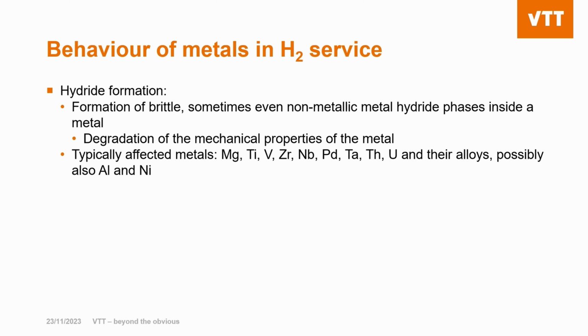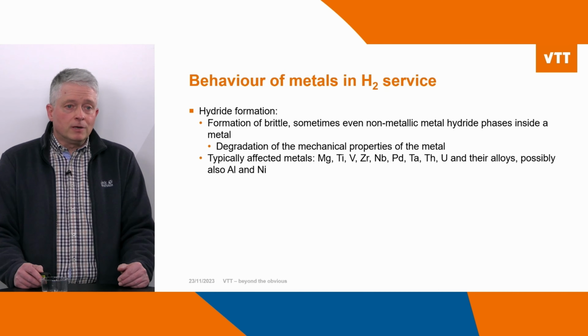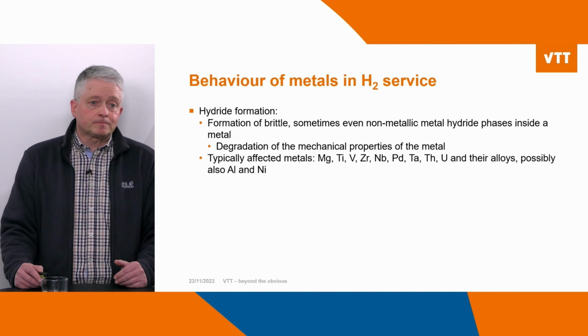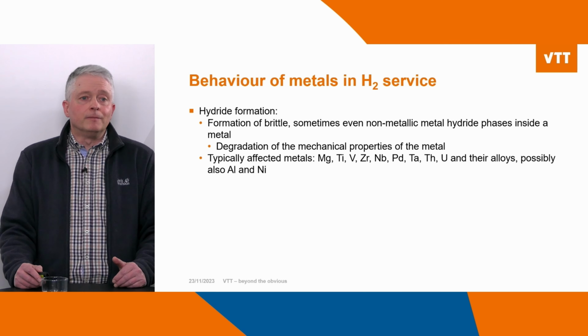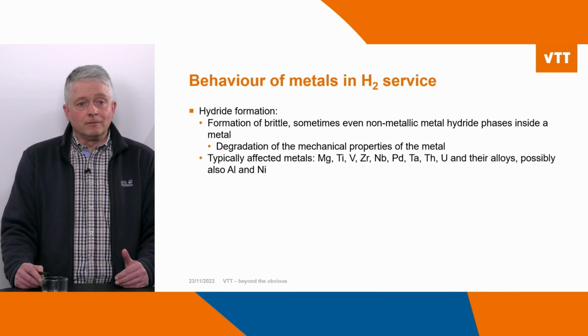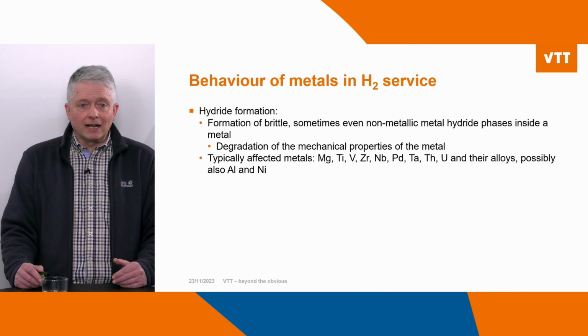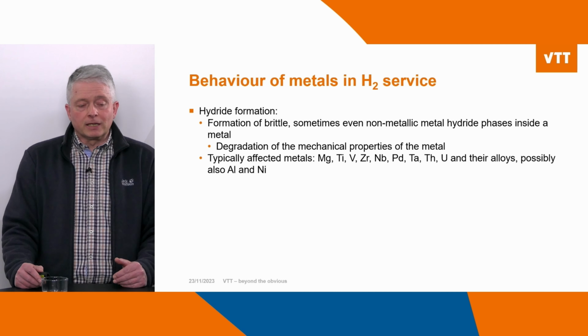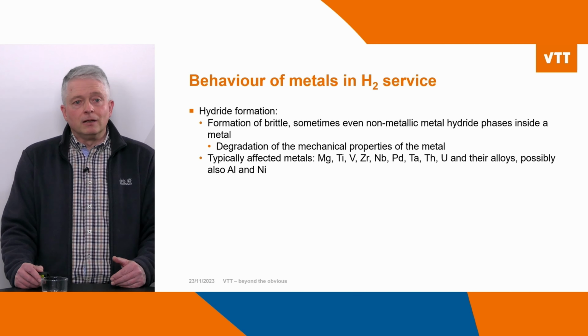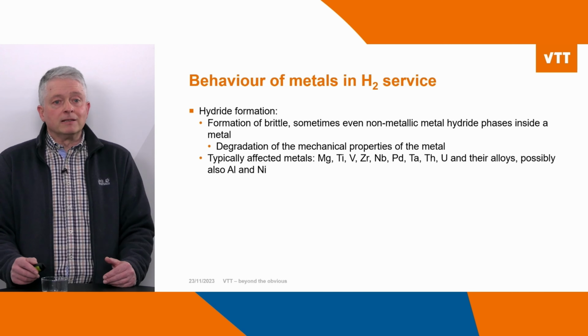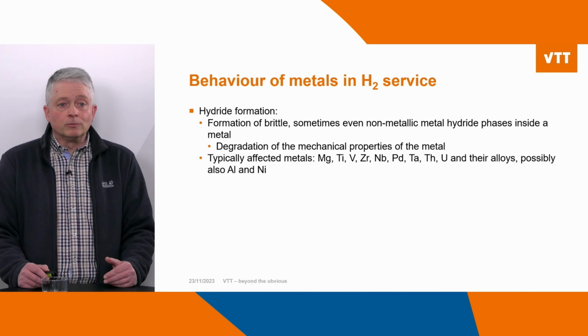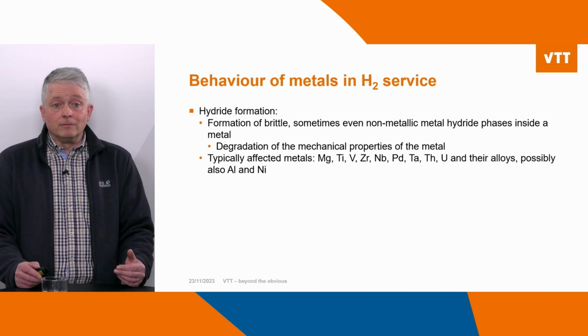Another failure possibility for metals with hydrogen is the formation of hydrides. Metal hydrides may form with hydrogen, and then the material is usually brittle. They may even be non-metallic, and cause a degradation of the mechanical properties of the material. Typical examples here are magnesium and palladium, and it is also discussed for aluminium and nickel.